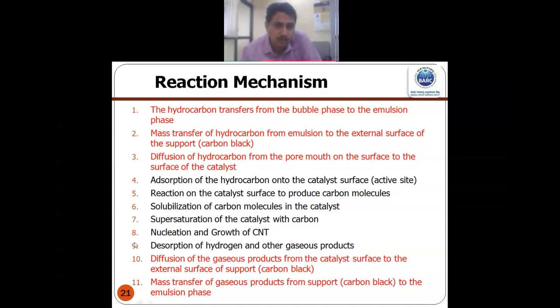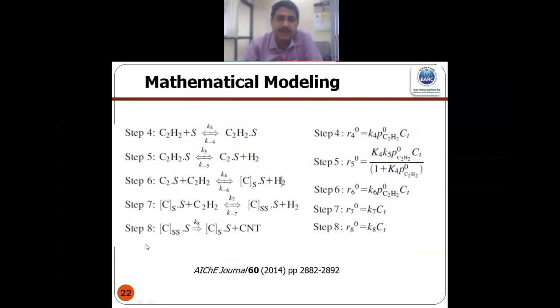So now these are all the 11 steps, and as I talked earlier, only steps 4 to 9 are important at low temperature, because the other steps are diffusion control, which is not the controlling mechanism. So we need to concentrate on the chemical reaction control regime, that is 4 to 9. So I can write the mathematical model related to those steps, like acetylene is coming and joining on S, which means site, and it is attached. Then from there you can have the carbon molecule and hydrogen can come out. Then once again this adsorbed carbon can react with the incoming acetylene and give rise to saturated carbon, and from saturated carbon it can go to supersaturated carbon, and finally supersaturated carbon gives rise to CNT and it comes back to the saturated carbon.